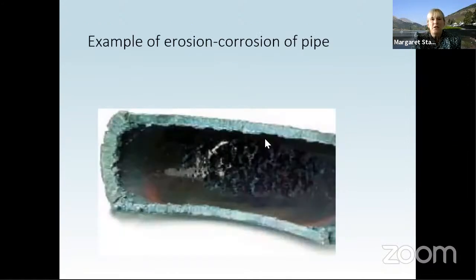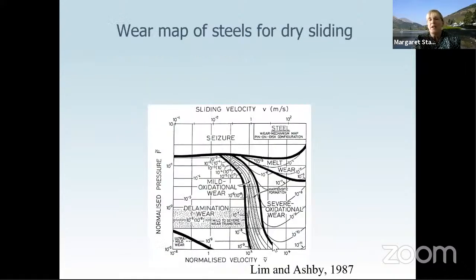So basically, what my group has been doing for many years, this is just an example of erosion corrosion of a pipe. We've got the pipe eroded at the bend that's associated with the high concentrations of particles. But what my group has been doing is to combine the Pourbaix diagram. This is electrochemical potential versus hydrogen ion concentration, and these are the various corrosion regimes. This is where we get iron dissolving. This is passivation. Mike Ashby's group in Cambridge, with Lim and Ashby, developed this wear map in 1987.